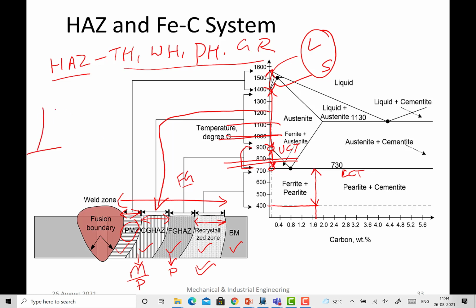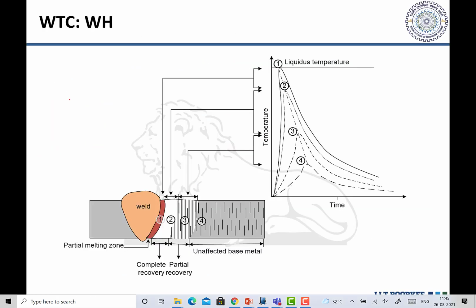If you take any metal and measure the temperature next to the weld nugget area and see what the peak temperature is, if you are aware of the peak temperature, you can easily estimate the kind of grain structure or the kind of phases which will be there in a particular region, in the coarse grain zone, heat affected zone, fine grained zone or recrystallization zone. So whether the temperature here is 1300 or 800, that will determine what you will be getting in this area.